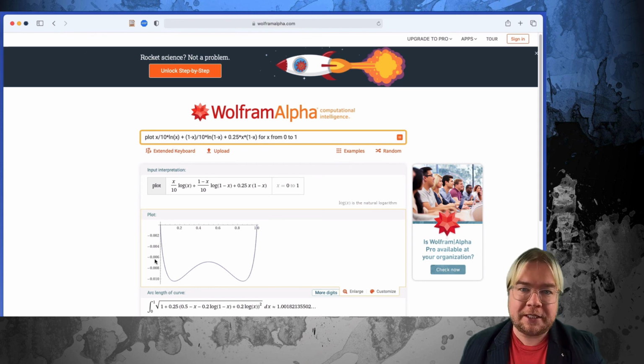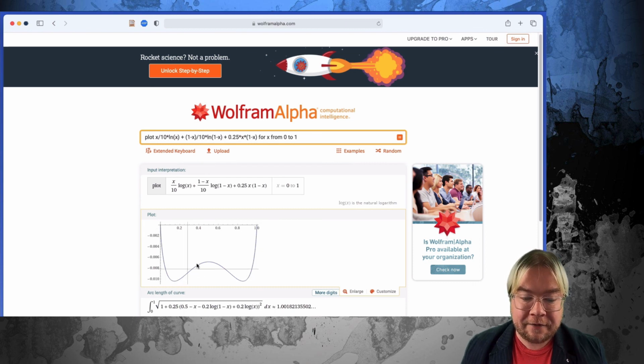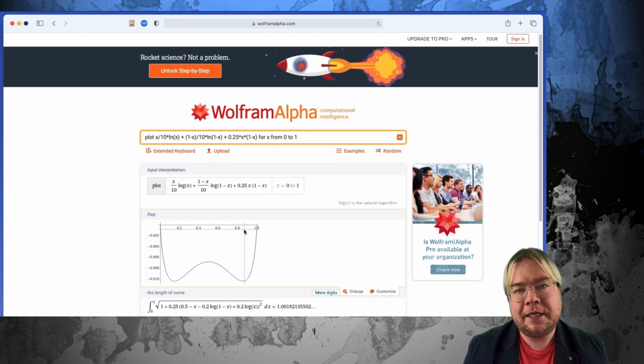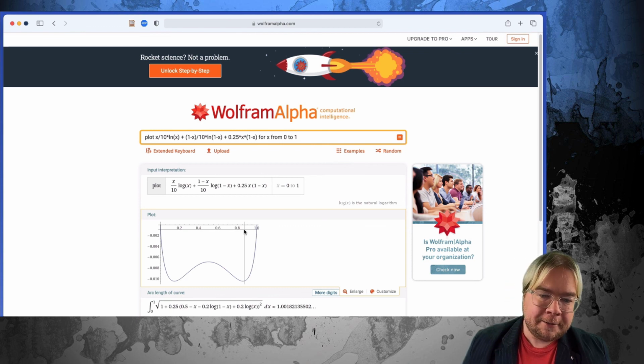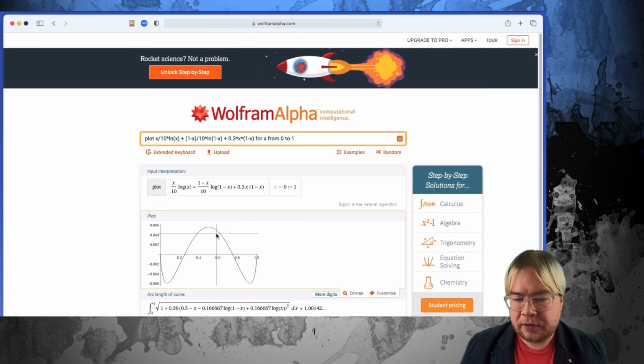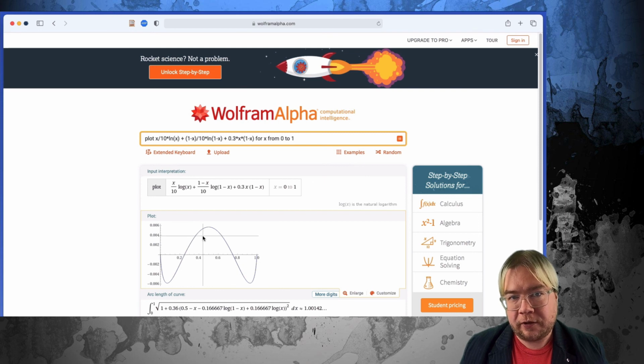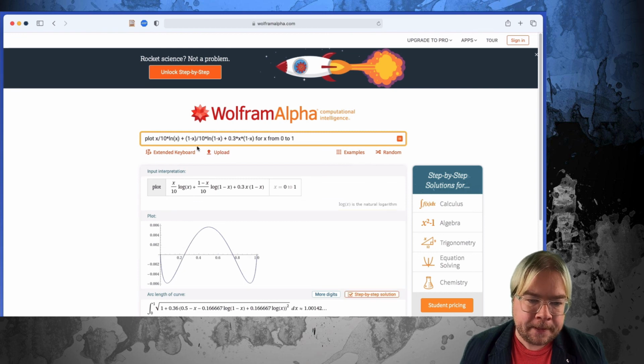And that's where this is a little bit different than what you've done before, because notice that all of these values are negative for the free energy of mixing. Even though the free energy of mixing is negative, the shape of this curve is going to lead to situations where the polymers will not want to mix together and they will phase separate. So there's a lot going on here, and that's why we really have to do a deep dive and analyze what we expect to happen. So for now, if you see this kind of shape for the curve, there's going to be regions that are unstable and regions that are stable. And so our next task is to do a stability analysis to see what we expect to happen.